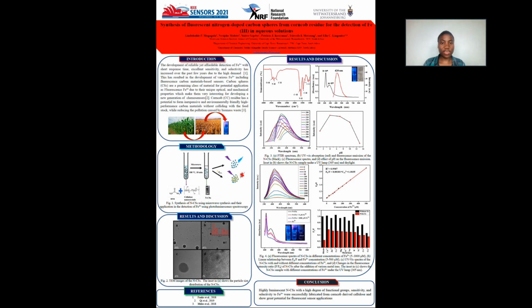The sensitivity of our nitrogen-doped carbon spheres towards the detection of iron 3+ was determined by preparing different concentrations of iron 3+ and incorporating them into the nitrogen-doped carbon sphere suspension. Now you can see that the intensity tends to decrease with the increasing concentrations from 0. This is because when the concentration is increasing, it tends to form a complex with the surface functional groups, therefore limiting the fluorescence emission of our carbon material.